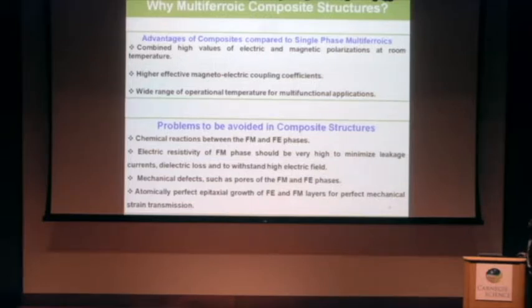So during the synthesis of composites, as it has ferromagnetic and ferroelectric phases, we have to take care of a lot of things. There should not be any chemical reaction between the ferroelectric and ferromagnetic phases, and the electrical resistivity of the ferromagnetic phase should be very high to minimize the leakage currents and dielectric loss, in order to withstand the high electric field. And during the synthesis, mechanical defects such as pores in the ferromagnetic and ferroelectric phases should be taken care of, and we should grow atomically perfect epitaxial multilayer or composite single layer thin films for perfect mechanical strain transmission.